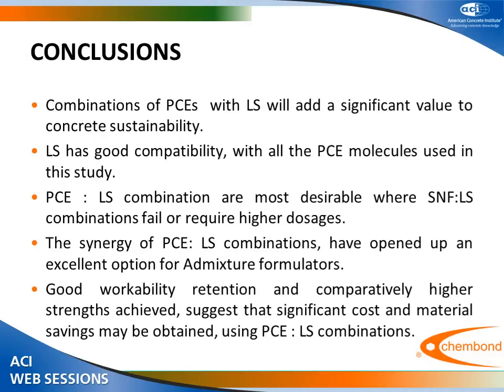So in conclusions, again, combinations of polycarboxylates with lignosulfonates will add significant value to concrete sustainability. We are talking about cost here, first of all, of combinations, and also the synergy which they are offering. Lignosulfonate has good compatibility with all the PCE molecules used in the study. Polycarboxylate and LS combinations are most desirable where SNF and LS combinations fail or require higher dosages. The synergy of polycarboxylate and LS combinations has opened up an excellent option for concrete admixture formulators. Good workability retention and comparatively higher strengths suggest that significant cost and material savings may be obtained using polycarboxylate and lignosulfonate combinations.